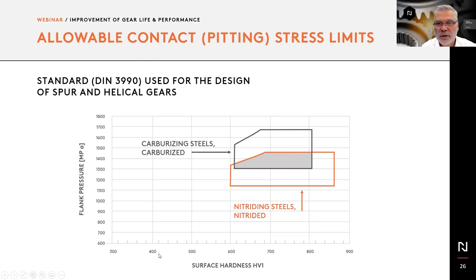One of the points of interest also in designing gears is contact or pitting stress limits. And this is taken from a German standard, the DIN 3990, which is used for the design of spur and helical gears. And you see that nitriding steels show a somewhat lesser stress limit. They do overlap with carburizing steels and better carburizing steels, but they show a somewhat lesser limit in terms of allowable flank pressure.